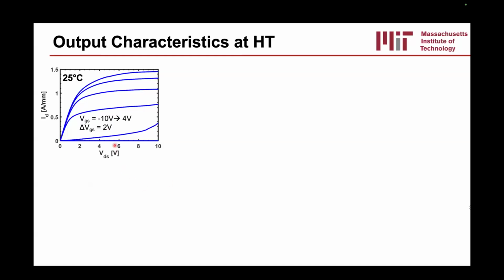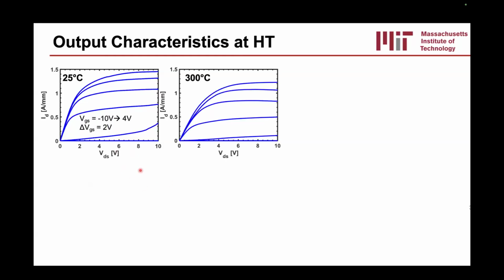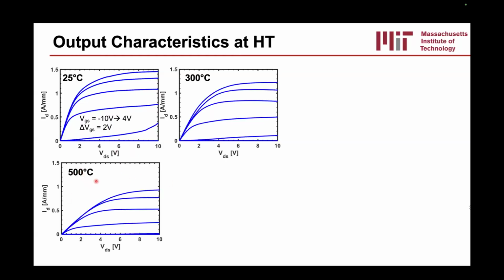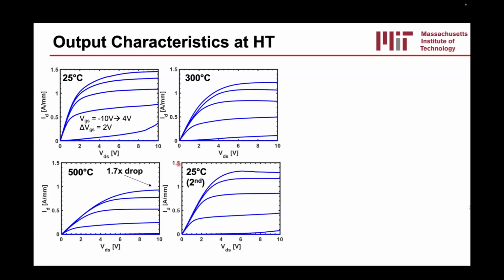That's what we did. We measured the output characteristics at 25C, 300C, and 500C. And you can indeed see that the current density doesn't drop by 10x. It drops by about 1.7x, from about 1.5 amps per millimeter to just a little bit under an amp per millimeter. Similarly, if we cool down the device and bring it back down to 25C, you can see that there is a little bit of change, but overall the maximum current and the on-resistance haven't changed much. And mostly the change I'll show you in the next few slides is due to the shift of the threshold.